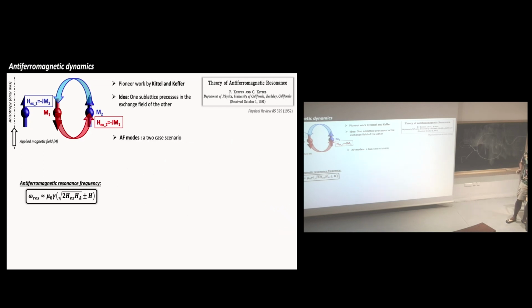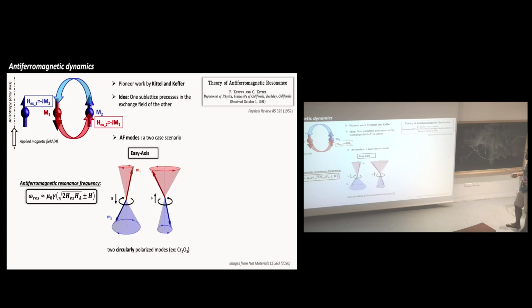There is another concept for the dynamics I want to tell you about. If you derive this, you can have different modes. So it's basically a two-case scenario. The first one, which I already mentioned a little bit, is the case of the easy axis antiferromagnet. The easy axis antiferromagnet is one of the simplest. Not only do you have the exchange, which wants the two spins to lie antiparallel, this we know, but then you have the magnetic anisotropy, which wants the spins to lie only along one axis. If you do this, then in this case you have this equation for the eigenmode.